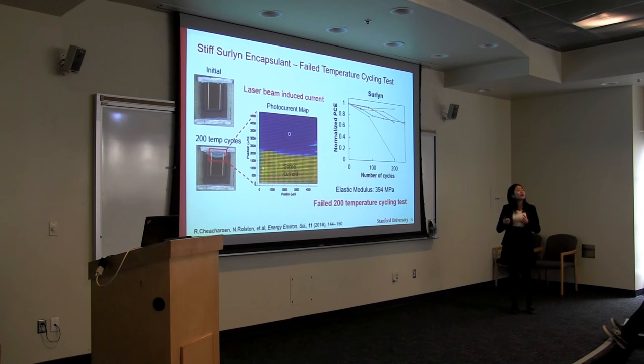I went back and looked at my encapsulant table, and I found that the elastic modulus is really high, almost 400 megapascal. Talking to the Dauskardt group, we know that Surlyn adheres really well to ITO and glass. So what happened during the temperature cycling is likely the Surlyn just pulls apart the PCBM layer, exposing it, and moisture gets in and degrades the perovskite, and that's why we see a drop in performance as shown in this graph. So it seems like we need a better, perhaps lower elastic modulus encapsulant to make it more flexible during temperature cycling.